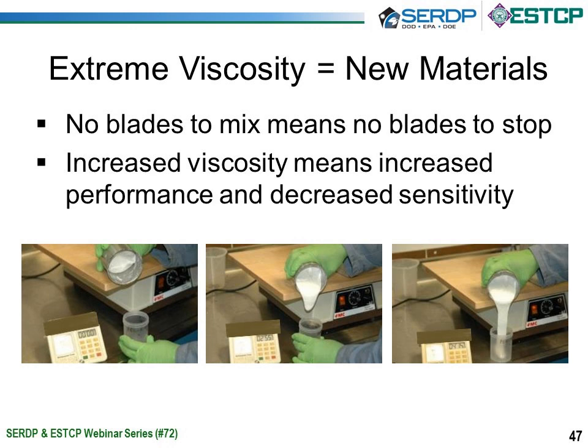And extreme viscosity for us means access to new materials that we couldn't get to otherwise in our bladed mixers. If there are no blades to mix, there's no blades to stop. And so you can get into viscosity regimes that are completely inaccessible with legacy technology. Increased viscosity in our world means increased performance. All of the plastic bonded explosives, rocket propellants that we normally work with, are formulated at the limit at which you can get solid oxidizer or solid explosive into a binder matrix. If you could put more in, you can get more explosive performance out.